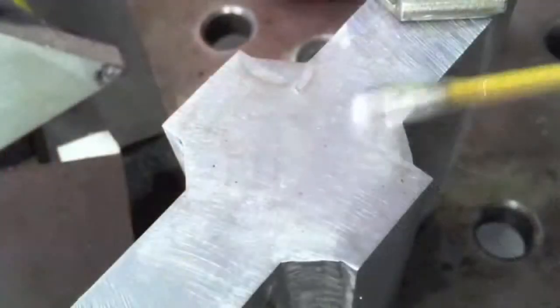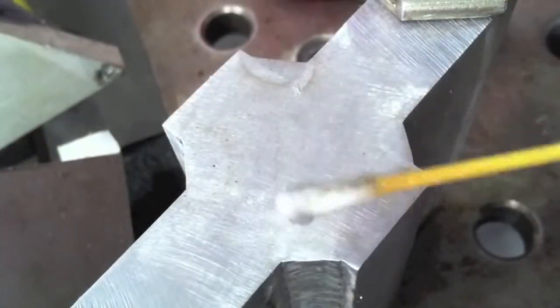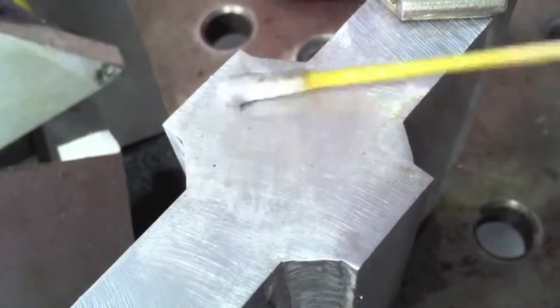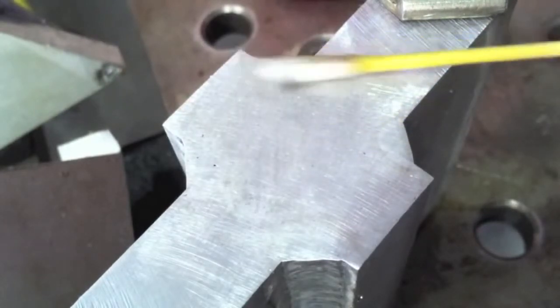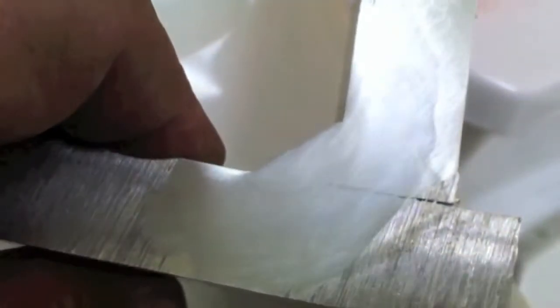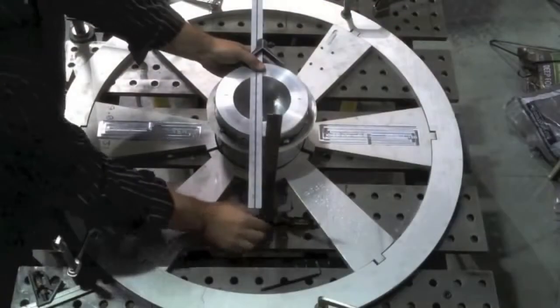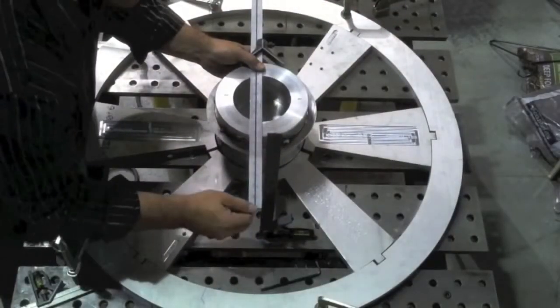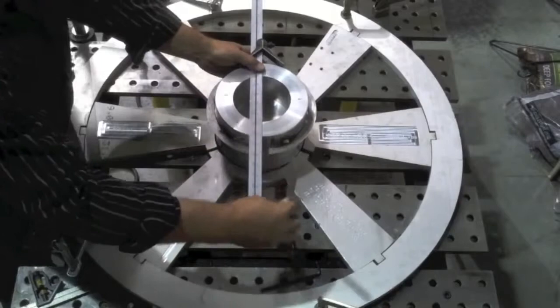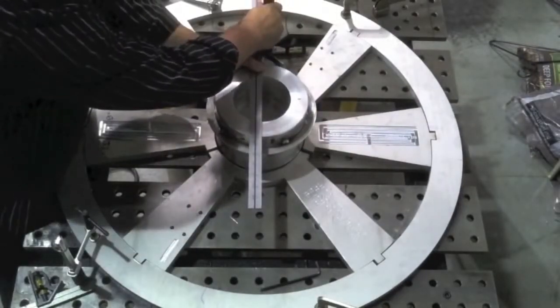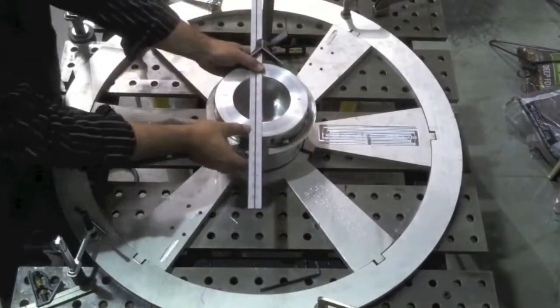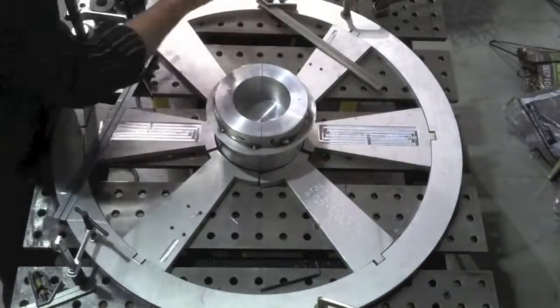Got as good a polish as I could on it, and then a little etch. And I just used a household product to etch here. A lot of household products are really high alkaline, and actually I used Drano here with a cotton swab to etch, and then kind of check my penetration. So I had a void in one of them, and it was the one that I welded first with no preheat, because the rest of them had preheat just from welding, heat build up in it. So I could tell I was gonna kind of need to throw a torch on this thing and get it warmed up in order for it to weld like I wanted it to.